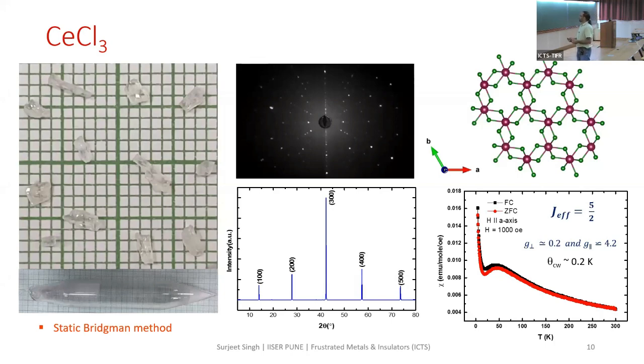We did some preliminary measurements. We see this very interesting hump over here in the magnetic susceptibility. As of now, we don't know why this is there. This is, by the way, not a Curie tail. This is the full cerium moment, because at much lower temperatures, it is supposed to order antiferromagnetically. So the cerium-cerium exchange, the theta Curie-Weiss, is about 0.2 Kelvin. So this hump is a little bit of a mystery as of now. Could be related to the crystal field excitations of cerium.